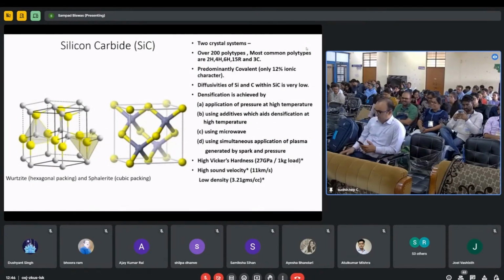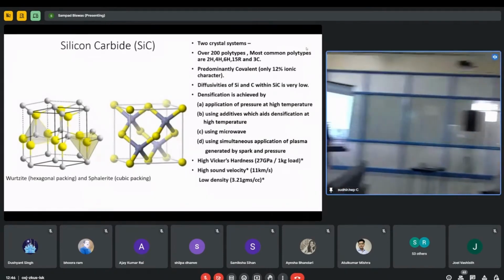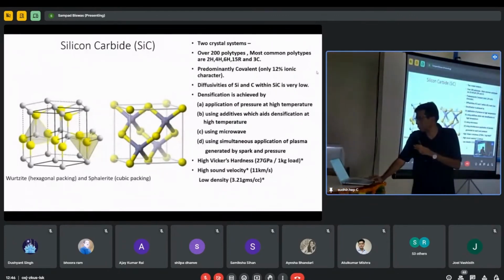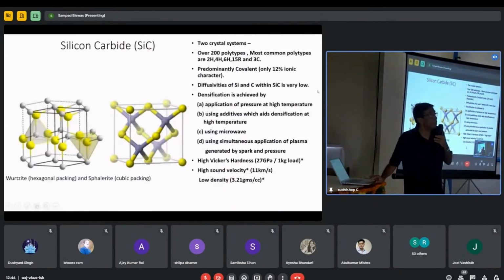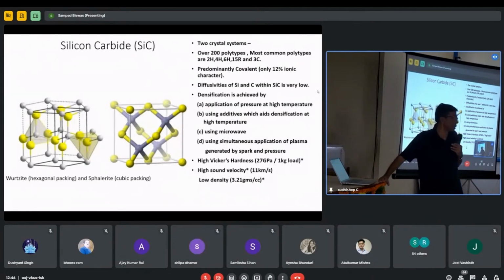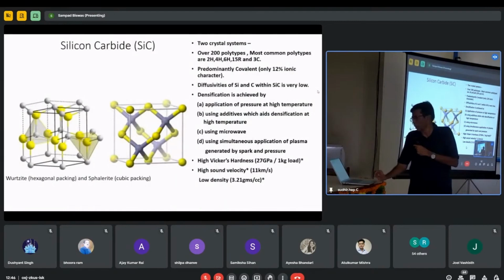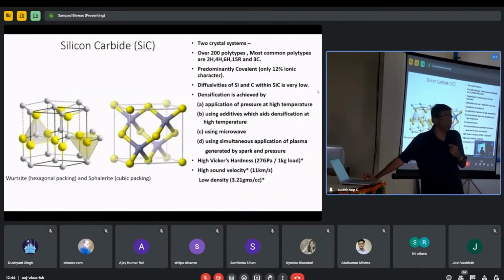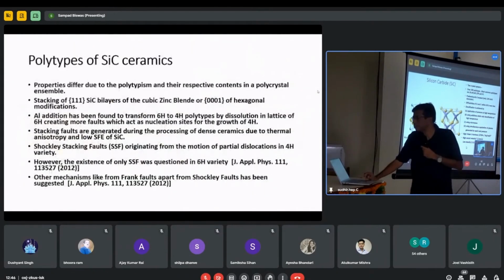So it has got a very high Vickers hardness, about 27 GPa at 1 kg load. And it has got a high sound velocity. That is most important: this high longitudinal velocity as well as transverse velocity within the ceramics. Solids have got much higher sound velocity. That is very important for armor applications. As well as that, it has got a low density, about 3.21 grams per cc.